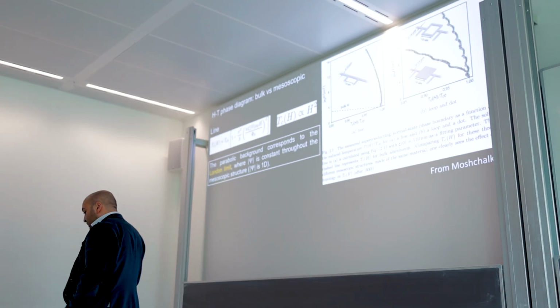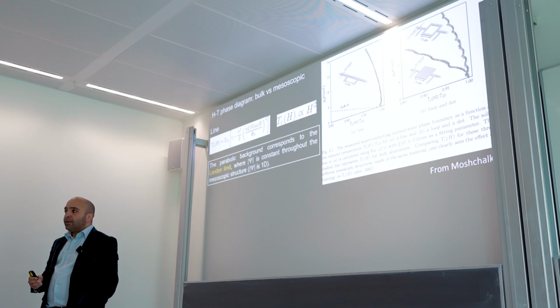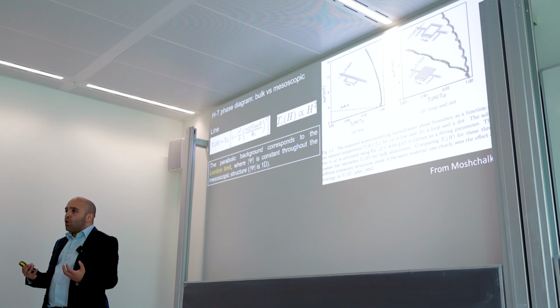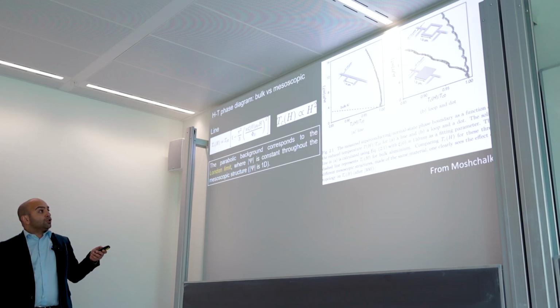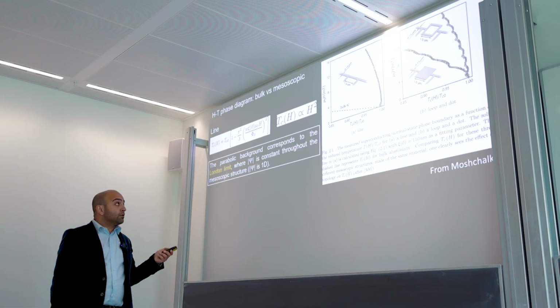The interesting thing about superconductors is that when you confine them, when you reduce your dimension, the superconductor actually becomes more robust against magnetic field. Here, for instance, I'm showing you the critical field and critical temperature of a bulk superconductor. This is for bulk aluminium, and this is for a nanowire, a 150 nanometer wide wire of aluminium. You see it has this parabolic shape and also a much higher critical field compared to bulk.